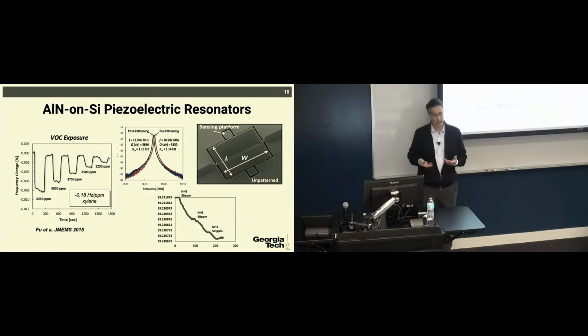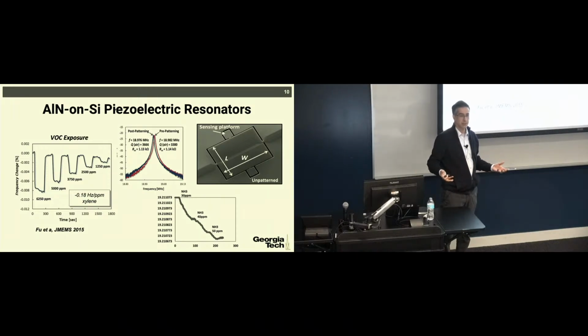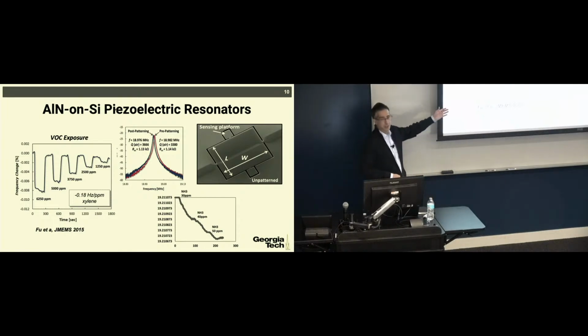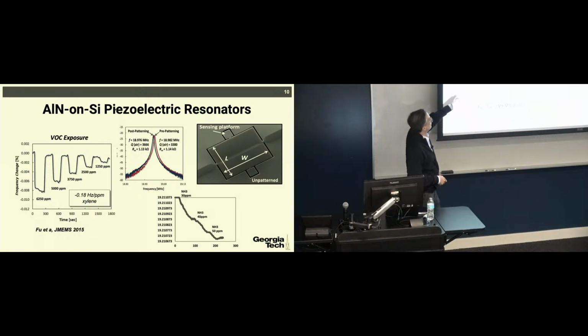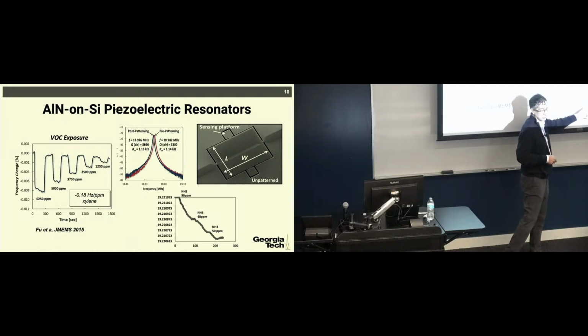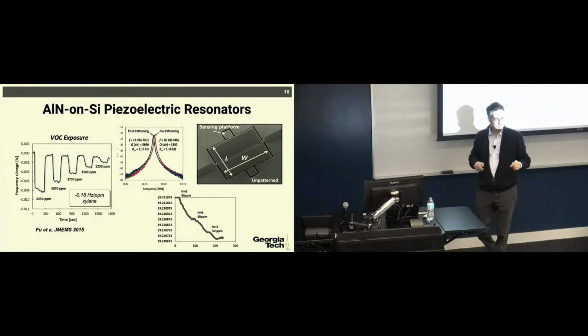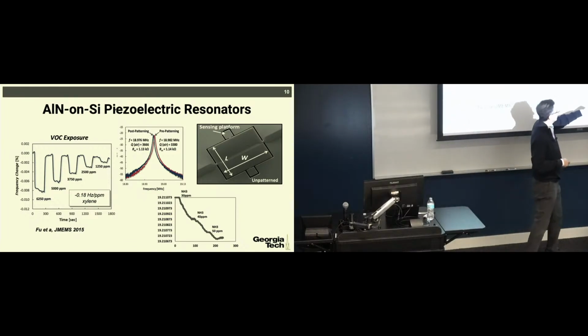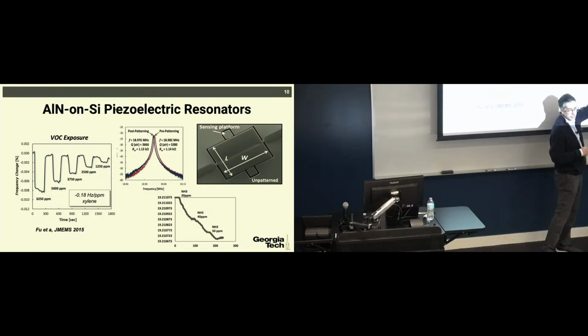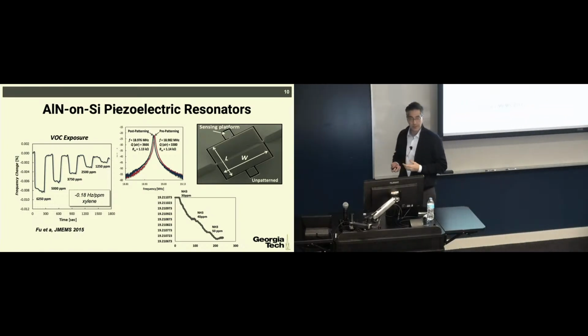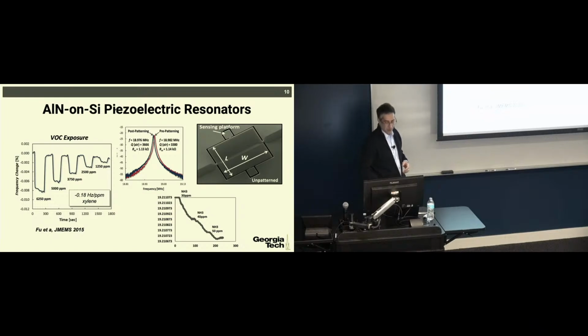So if you build an oscillator out of this resonator, and then expose the resonator to an environment where that molecular recognition layer is active, then you can actually create a biochemical sensor. So for example, we made a bunch of VOC sensors, volatile organic compound sensors, and we showed that by just cycling the concentration of xylene, which is a type of VOC in the environment, the frequency would shift. Another more sensitive application was sensing ammonia. So this is an ammonia sensor, again, using the same type of device, just patterning the platforms with the molecular recognition layer, which was a polymer for ammonia. And you can see that we could actually detect easily 10 ppm change in the ammonia. So this was a device that could detect sub-ppm change in the ammonia concentration. So there are now applications.